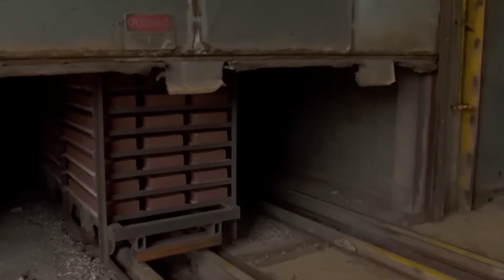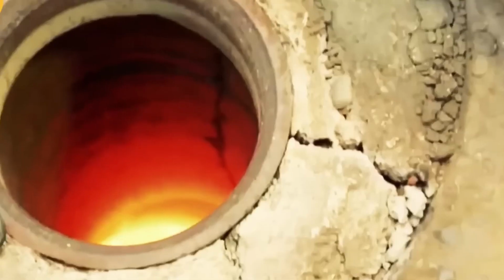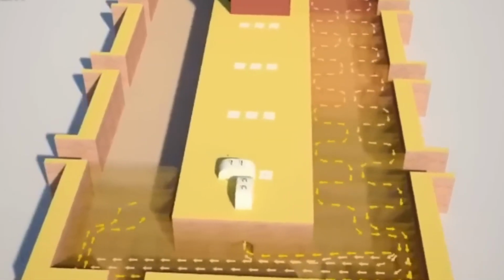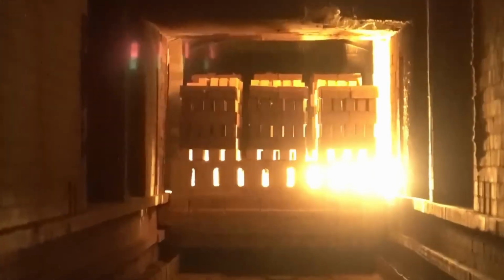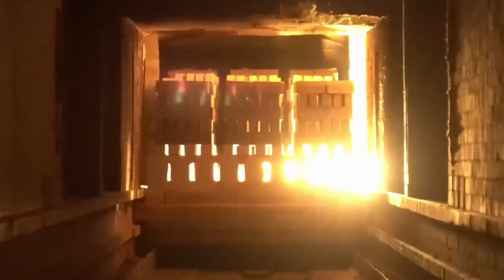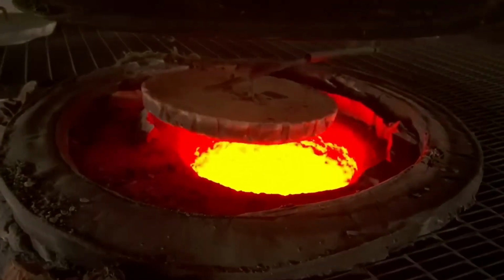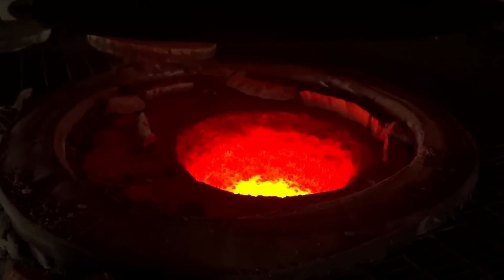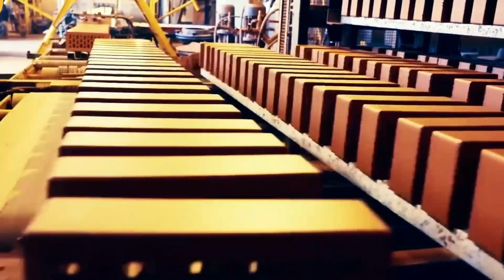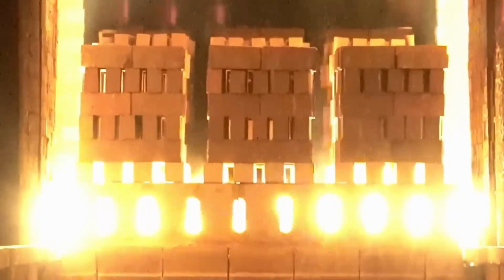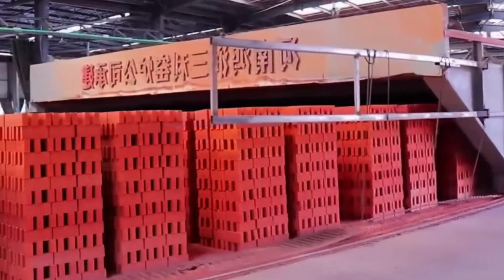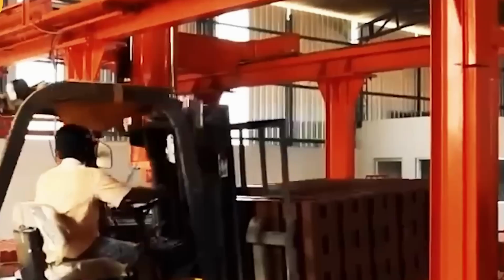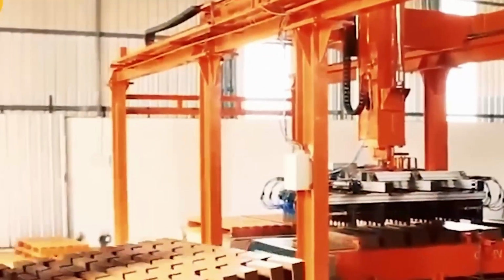The color is also determined in the kiln. Iron oxides produce red, orange, or brown tones depending on the temperature and the amount of oxygen available. In an oxidizing atmosphere, iron tends to produce reddish colors. Under more reducing conditions, darker or bluish tones may appear. The clay composition, the firing time, and the internal environment of the kiln all contribute to color variations. In common bricks, these variations are acceptable within certain limits. In facing bricks, color control is much more demanding.